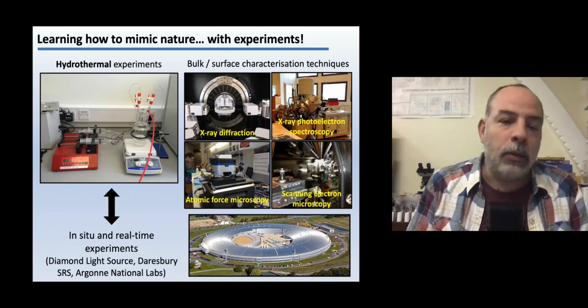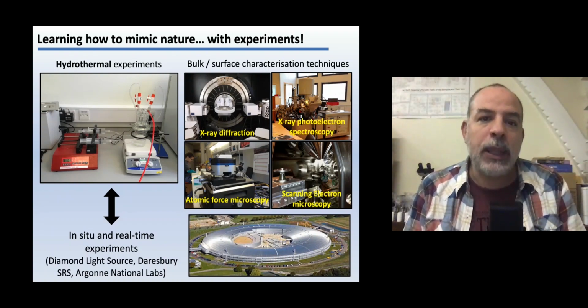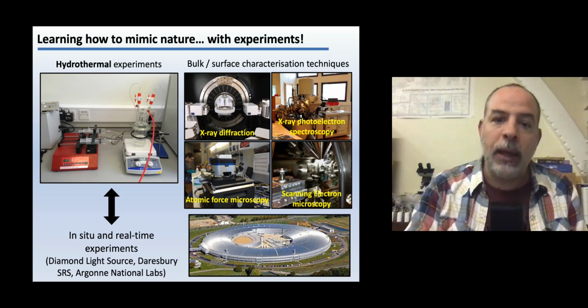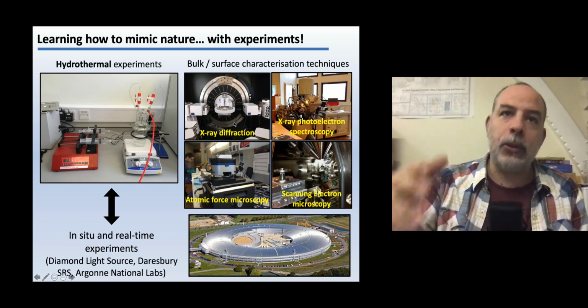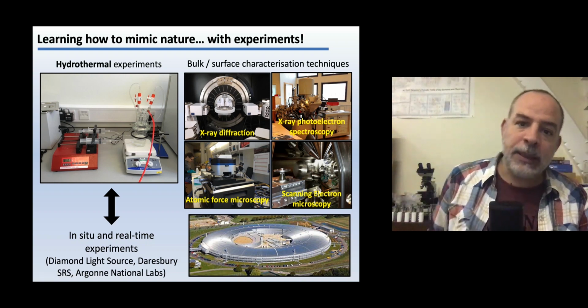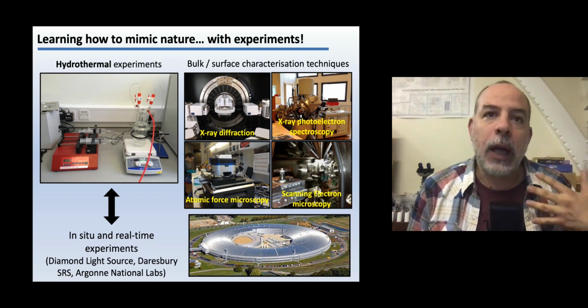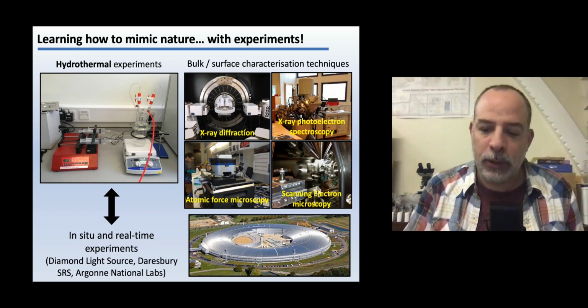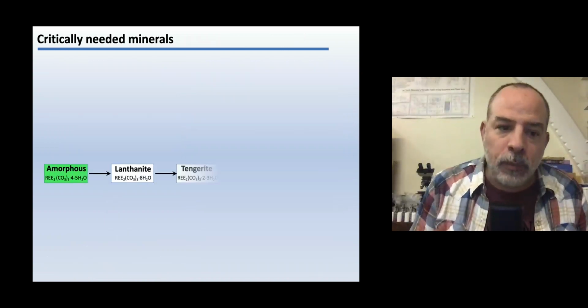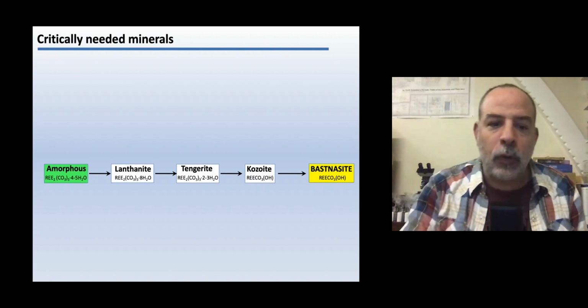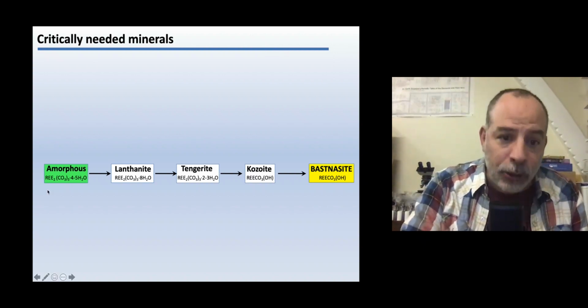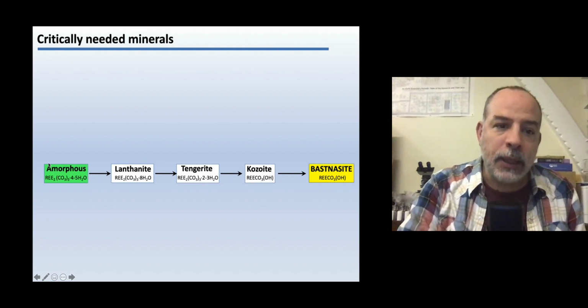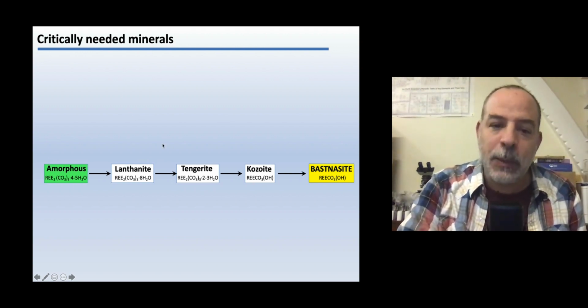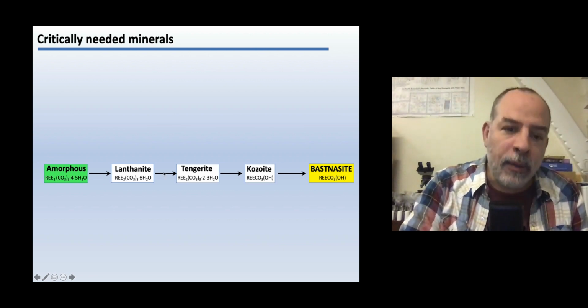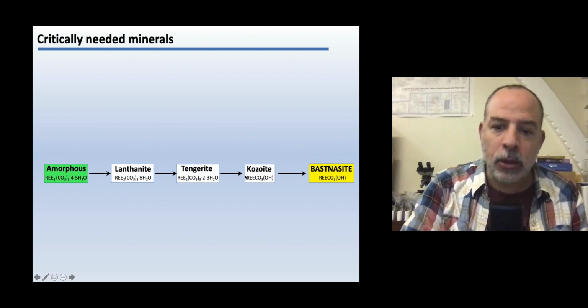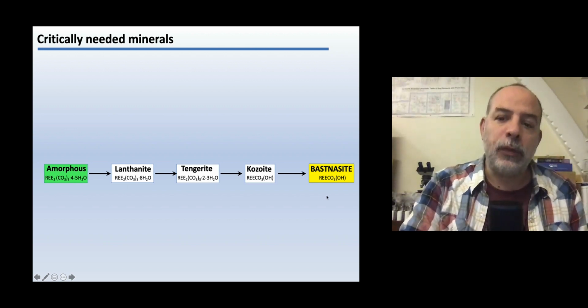So, as I told you, what we do is to try to mimic what happens in nature by using experiments. So we combine first offline experiments, laboratory experiments, with synchrotron experiments, in this case to understand how a mineral like bastnasite forms. So we have seen that bastnasite forms from an amorphous phase, and we have synchrotron data showing us that this transformation from amorphous to bastnasite takes place via different polymorphs. They are named lanthanite, tengerite, kozoite, and these ones slowly transform into bastnasite.